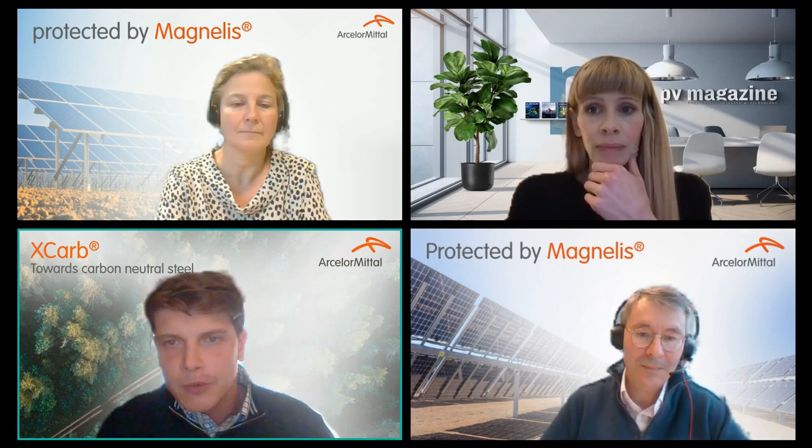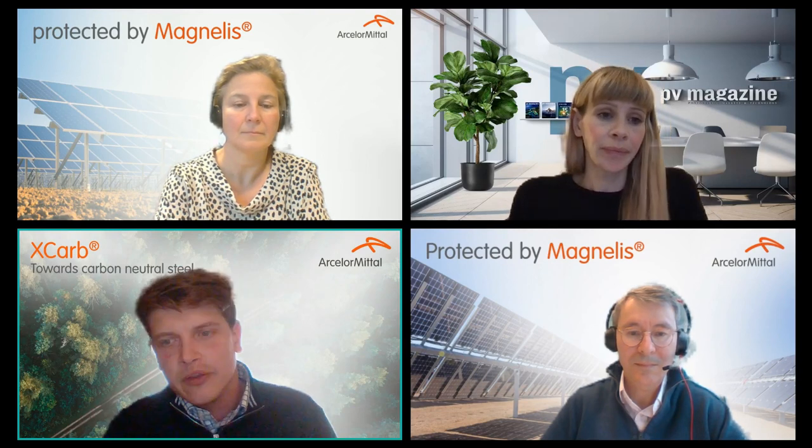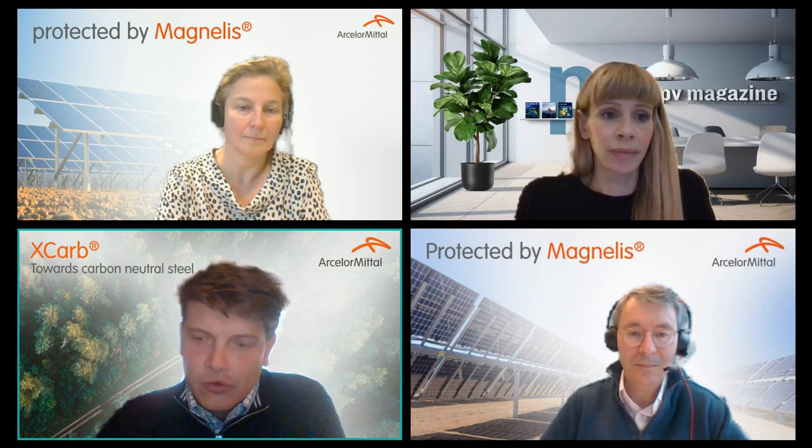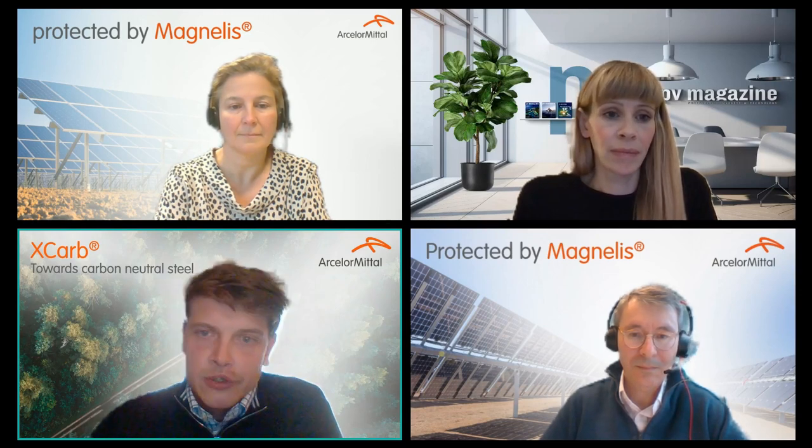Hugo, looking at how you measure the environmental impact of mounting systems — what tools and methodologies do you use? So what we do is a life cycle assessment. It's really important when talking about product-level CO2 emissions to not only count the direct emissions from the steel production process, but also look upstream and count emissions from the electricity and energy we consume, as well as the raw materials and their transportation to our gates. The system boundary we use is called cradle to gate — right from the mine site up to the gates of the steel plant. For Magnélis, we publish this EPD following Euro norm standards for EPD calculations, verified by a third party, which is IBU, the German authority on EPDs.